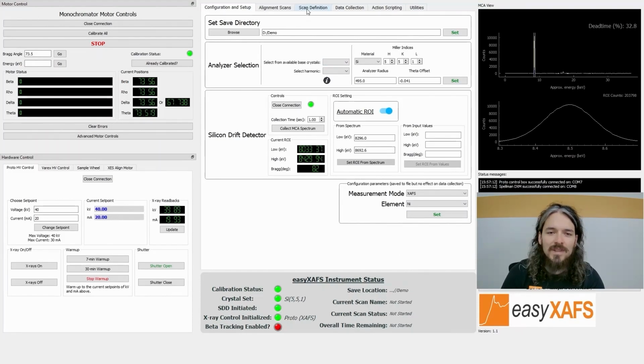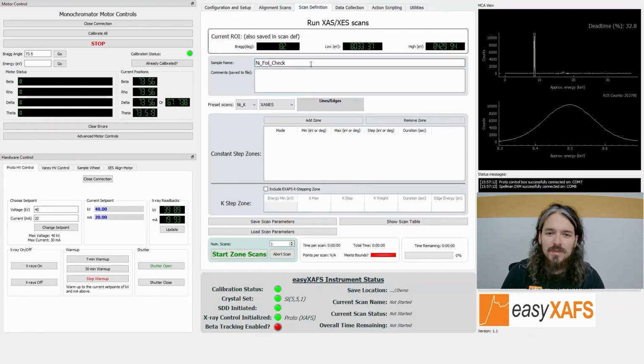For the scan definition, I'll give the sample a name. Here we're going to do a quick nickel foil check. Using the preset scans, I'll select the nickel K and the quick check mode. You can see this is a single constant step zone. We'll scan the energy of the beam between these two energies, just with a coarse step size and a very short duration. This gives us a time per scan of just 20 seconds. This just gives us a chance to see that the sample is in the position that we expect and that we're properly capturing the absorption edge that we want to see.